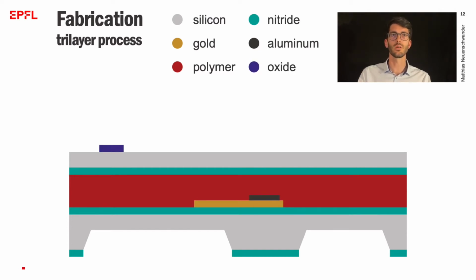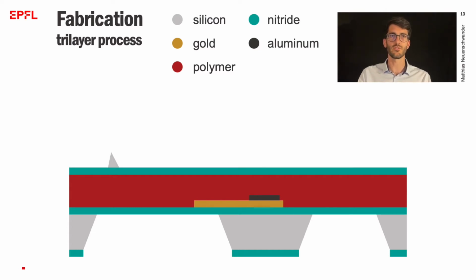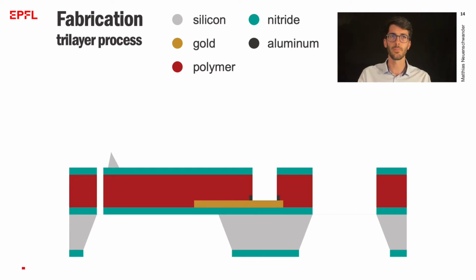To do so, we make a mask out of silicon oxide through lithography and wet etching. This mask is under-etched, again in KOH. We end up with a tri-layer membrane in the middle, a silicon chip on one side and a sharp silicon tip on the other. To finally obtain a cantilever, we pattern its shape through lithography, then dry etch through the tri-layer structure. This also opens an access hole to the bonding pads at the same time.